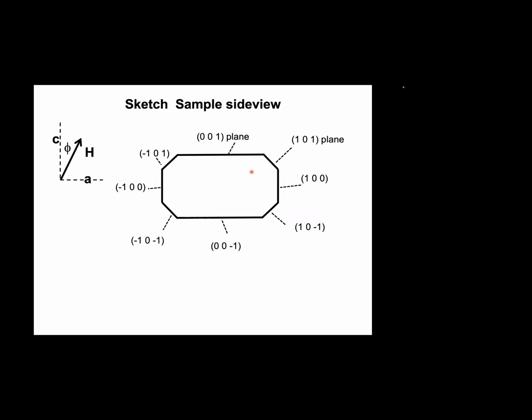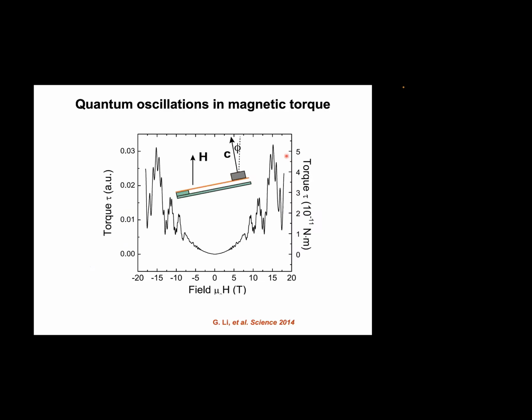To make it clear, this is the side view. As you can see, we rotate within this plane. We have 2 families, each containing 4 planes. That's how we do it, and this is our very early data when we look at magnetic torque versus magnetic field. As I said, at low fields it's quadratic, it's a paramagnet. As we go to stronger fields, 5 or 10 Tesla, we start to have these wiggles. We even have some slow wiggles and fast wiggles, which means there's a lot of things coming out as we try to measure the magnetic torque.